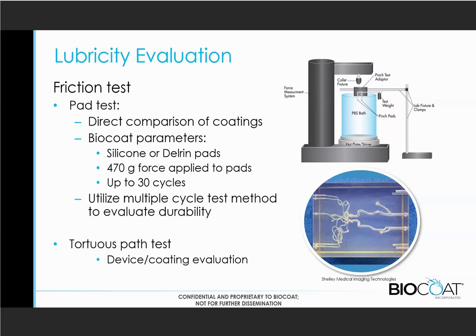And so the first part is a lubricity evaluation, where you're trying to see just how slippery this coating is, as well as the durability of that coating during the time of use. So I've got two examples here of how we at Biocoat do evaluations. The primary one we do is what we call a vertical pinch test or a pad test, where we take two pads and plates that we squeeze together.